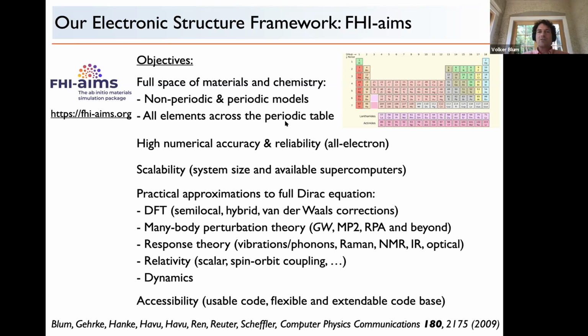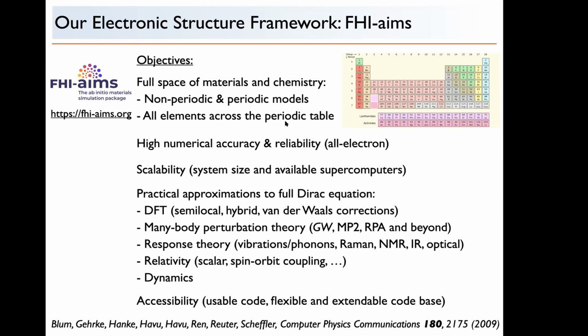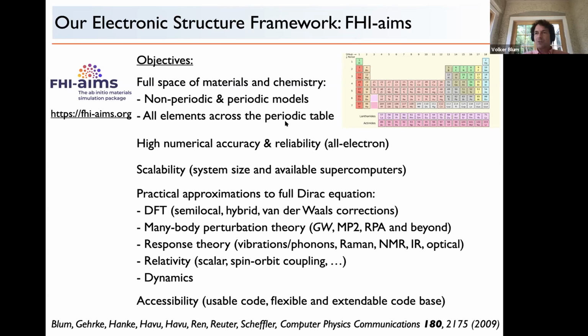Then, in order of questions: can we perform structure prediction using FHI-aims based on XRD data? It's a good question what you mean. Yes, if you have XRD data as input for your calculation, that's great, because you can actually use FHI-aims to post-relax. That gets you a little bit away from the XRD data in terms of lattice parameters. But if you have a complex material, it does have the advantage that it fixes issues that might be in the XRD. For instance, hydrogen-carbon bond lengths may be fixed by an XRD program, but they're not fixed at the right bond length. And so you can use an XRD input in FHI-aims and just optimize, and you get a structure that is much more reasonable in terms of CH bond lengths.